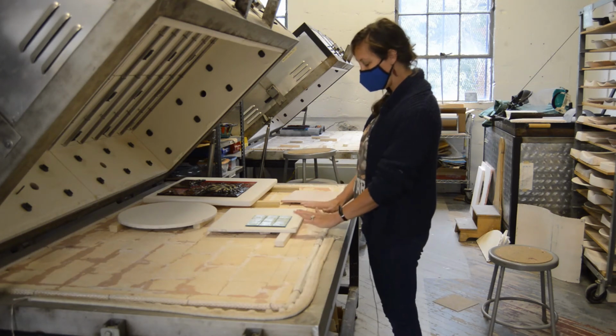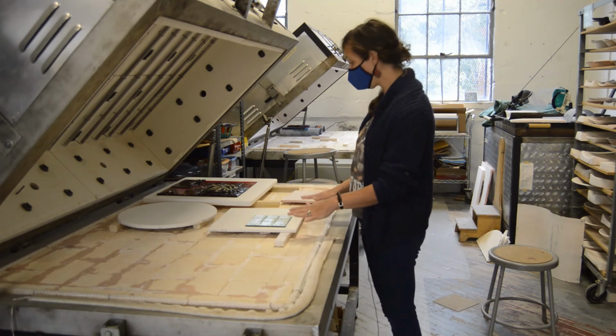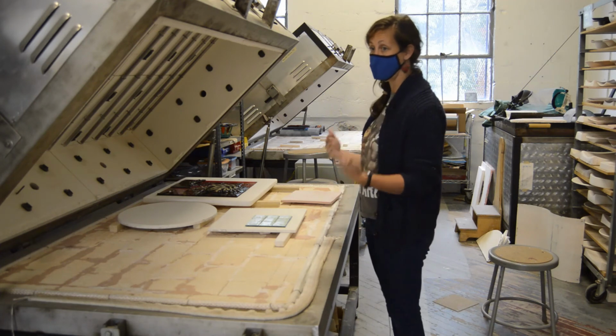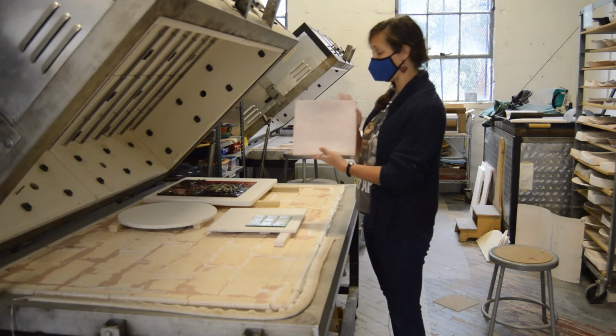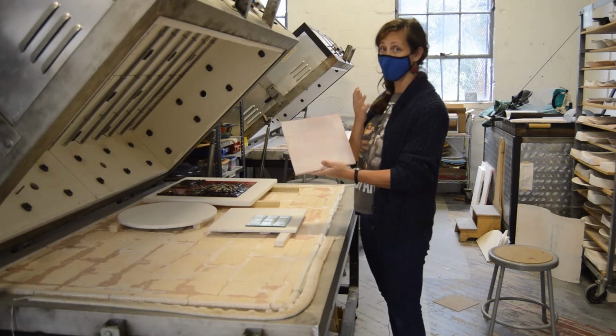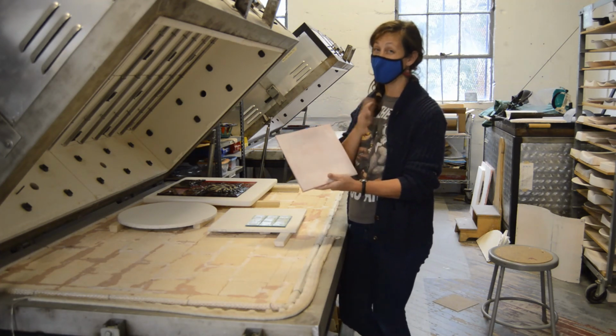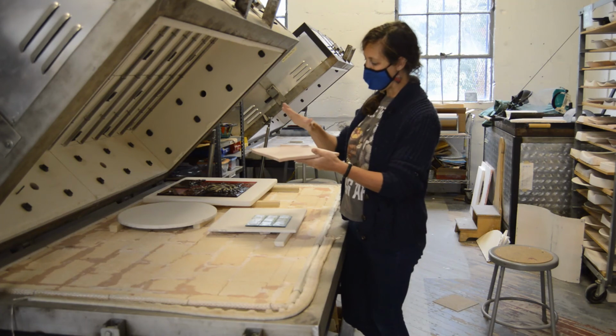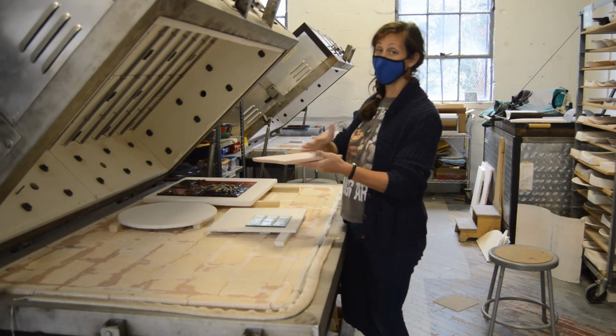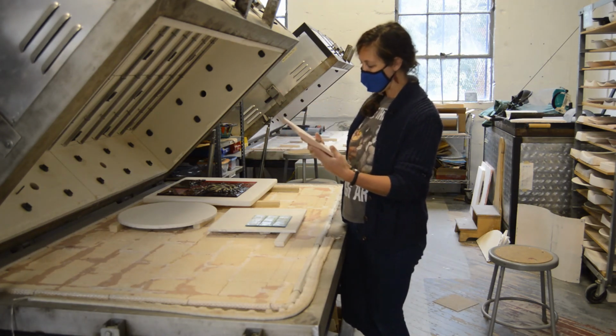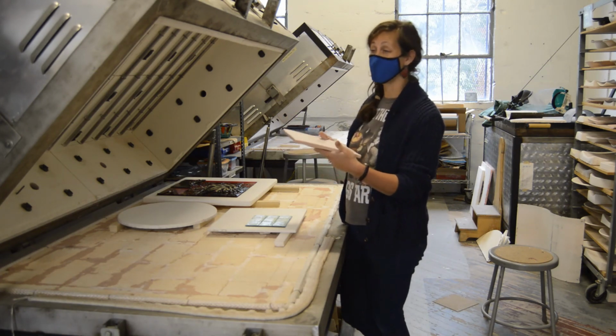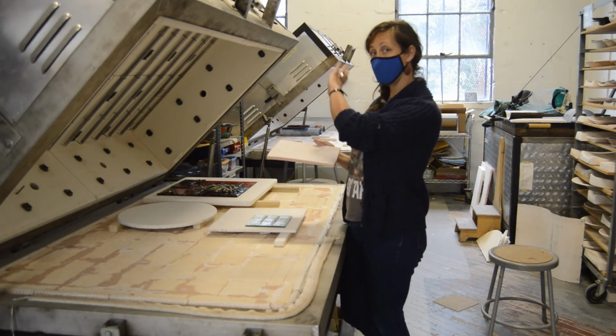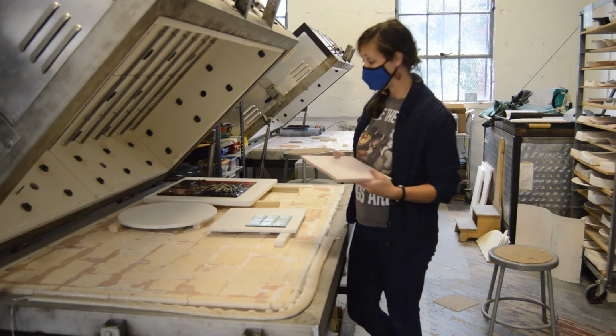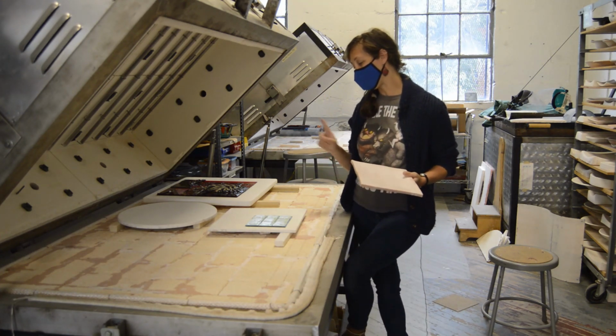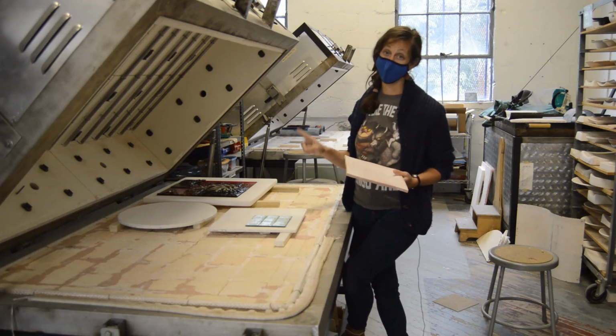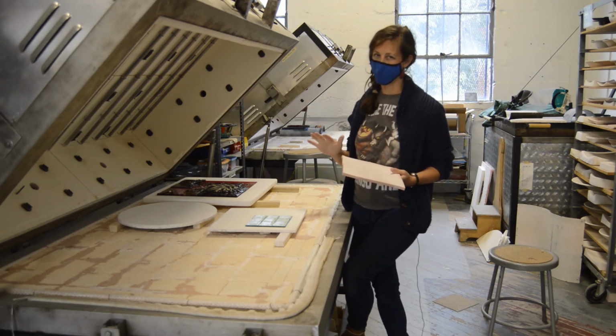So again, the first thing we're going to do is fire this flat together, and then after it comes out of the kiln as a fired piece, I'll put it into the kiln a second time over top of a ceramic mold. Take it to a lower temperature, about 1250 degrees, and it'll slowly take on the curvature of the mold that it's on top of. Even though it's getting a little cooler, it's still going to take around 12 hours to get to temperature and about 12 hours to get down. So it takes at least 1 full day for each firing. 2 days is probably a better guesstimate with that.